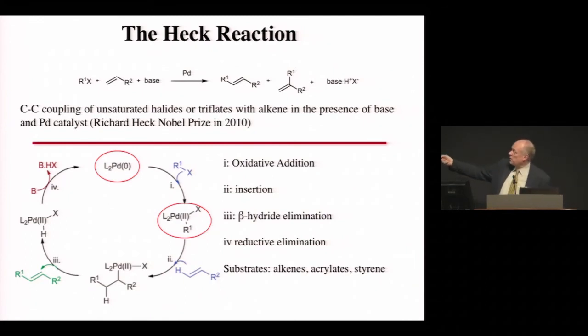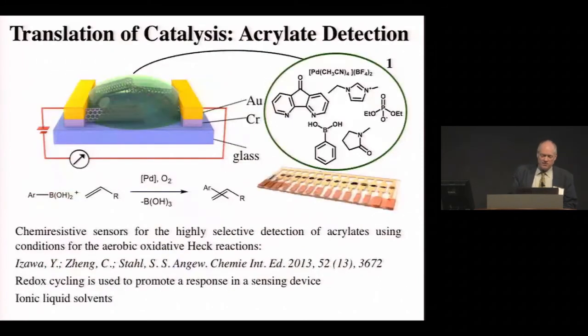Now it turns out we've done this in a classic sense with aryl halides, but the system that works best is a system that was invented by Shannon Stahl at University of Wisconsin, where he came up with something called the oxidative Heck reaction. So instead of using an aryl halide, he uses this boronic acid, which in the presence of oxygen essentially conducts that first step. So it basically takes the palladium-0 and puts a benzene ring on it, okay? Or a phenyl ring attached to it.